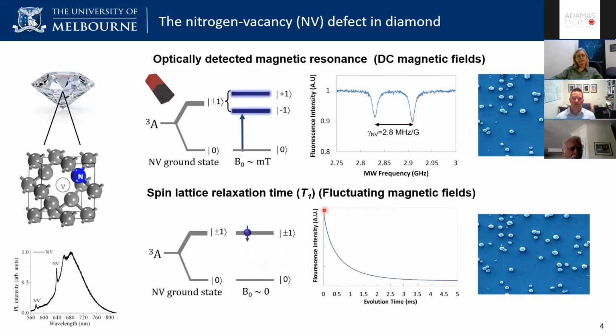And so you'll start off with some strong intensity when the electron spin is in the ms equals 0 state. And as we increase the dark time, or the periods between the optical pulses, we'll see that spin relax. And that'll have a characteristic time associated with that, which is referred to as the T1 relaxation time. So the 1/e time is that T1 relaxation time.